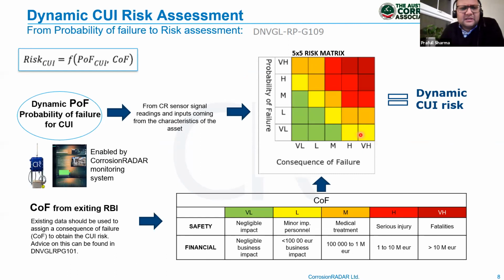Now, how does this happen? For the probability of failure in this example, we are using RP 109 DNVGL guidelines. Similarly, API 581 is another guideline. Normally, the risk assessment uses a 5x5 matrix, probability of failure and consequence of failure. The consequence of failure does not change over time. It may be safety or financial. It depends on the type of asset and fluids. But the probability of failure can change over time because of, say, water ingress and changed conditions. And that's what we make variable rather than static using monitoring, and that's what enables dynamic CUI risk assessments.